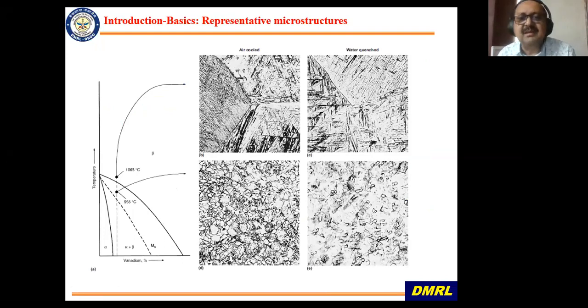Here I'm just trying to correlate some of the microstructures so that you appreciate the changes that you get, because these have direct impact on the mechanical properties. Here again on the left hand side, I'm showing a pseudo binary phase diagram, and this is an alloy like Ti-6Al-4V. Now suppose you have heat treated in the beta phase, then you will get very big prior beta grains, and if you air cool it, then you will get alpha, which is slightly coarser, and if you quench it faster, then you might be able to get martensite. That depends again on the cooling rate and the alloy. And then if you have deformed it in this regime and then you are heat treating here, you get a certain amount of primary alpha and the rest transformed beta. I will show you the exact SEM microstructures, but you get much finer grain sizes if you have deformed in alpha plus beta and are heat treating in this regime.